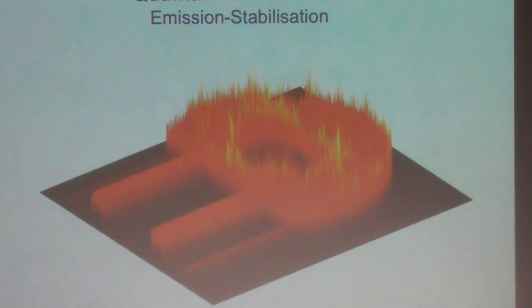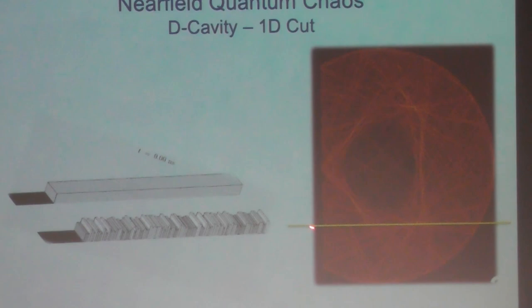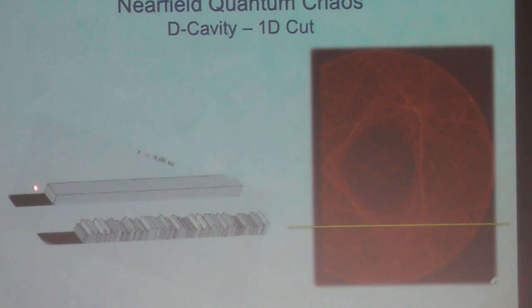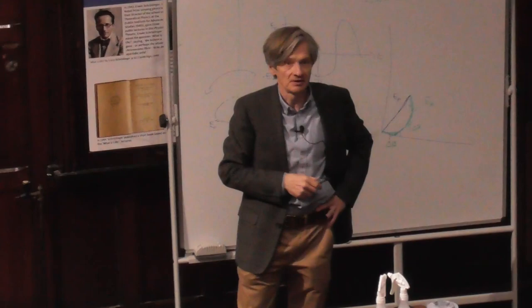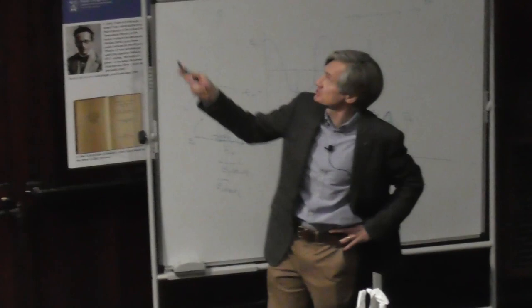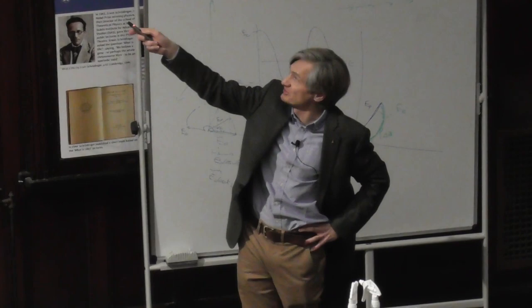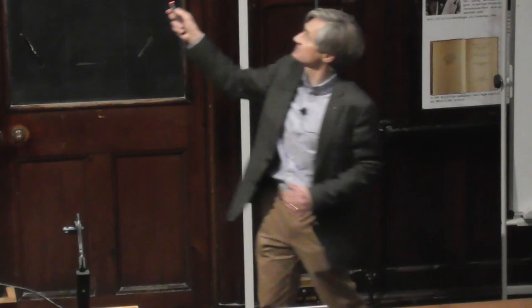And you can see that in order to model this, we came up with a description where you would literally look at a cut along that direction and compare that laser along something which is completely flat, homogeneous across that, and something which has a sub-wavelength random way how the refractive index is distributed on that. That's again folding back to the theory and here now taking into account the beauty of the semiconductor, which means that it's not two levels, but rather many bands. Makes it just a little bit more complex, but the physics is very similar. And these bands now then create a so-called gain structure and refractive index change.